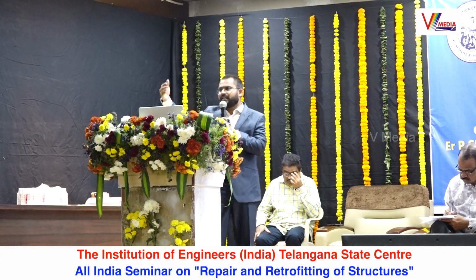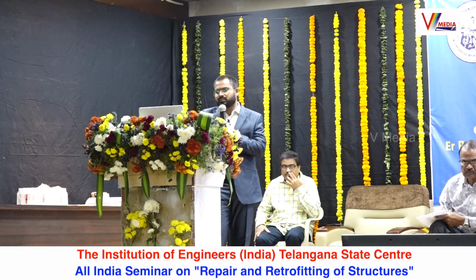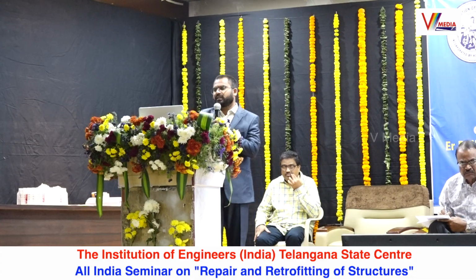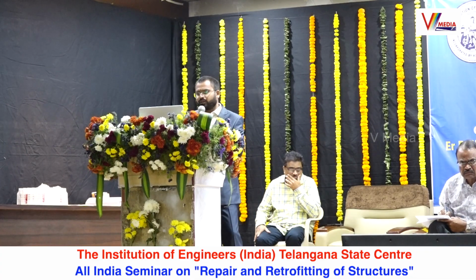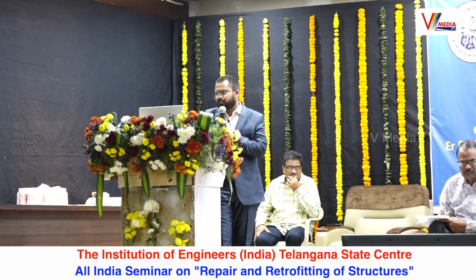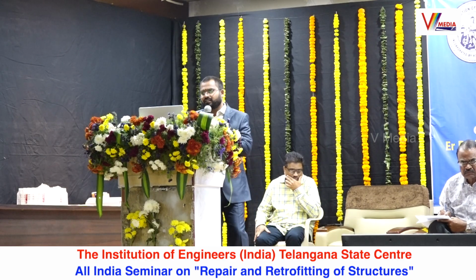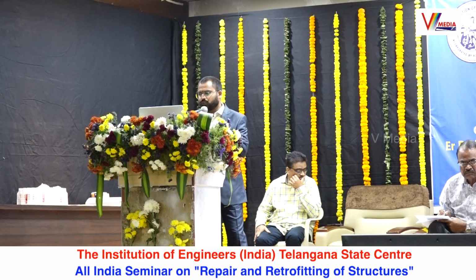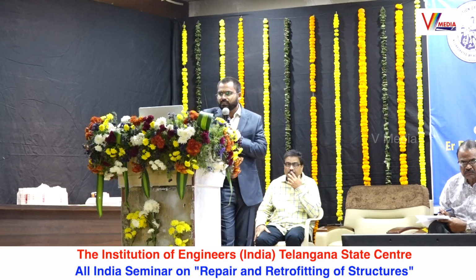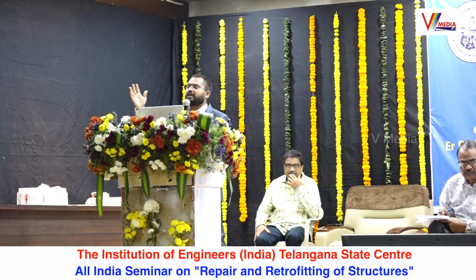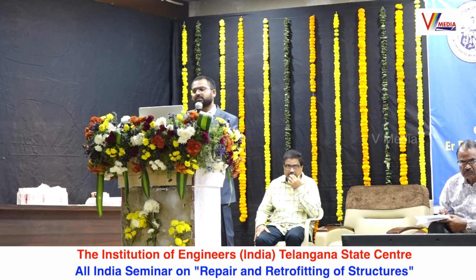There are some grading charts given for the ultrasonic pulse velocity test based on the grade of concrete. If the UPV value is greater than 4.5, then the concrete is said to be in excellent condition. And there are some factors, such as reinforcing bars. I hope IEI will share this presentation with you all. So these are some tips. You can also estimate the depth of a crack using ultrasonic pulse velocity.